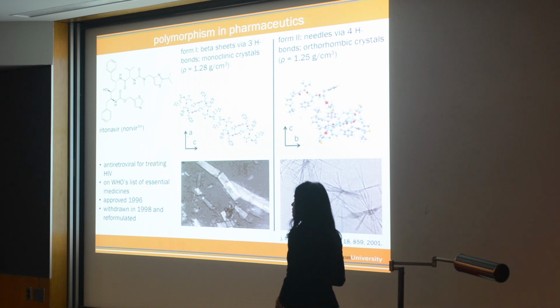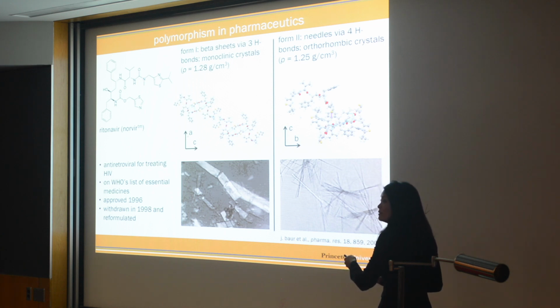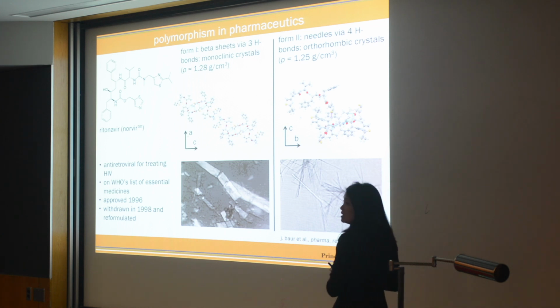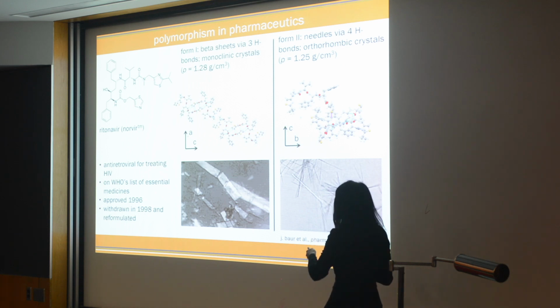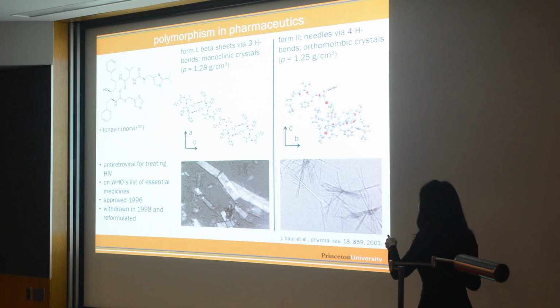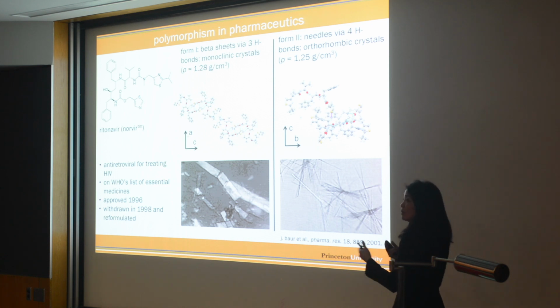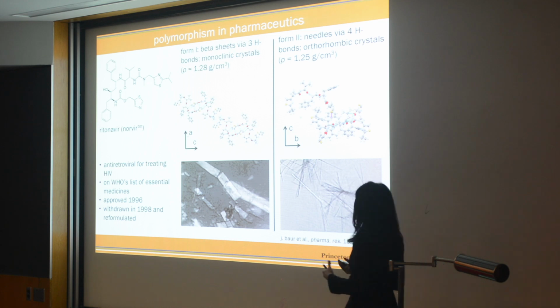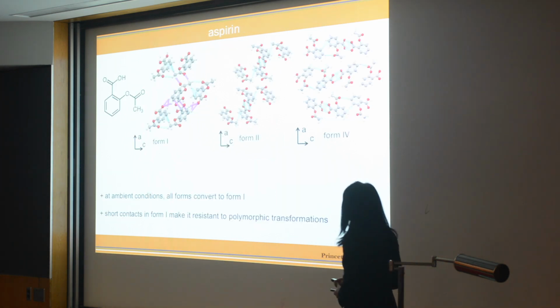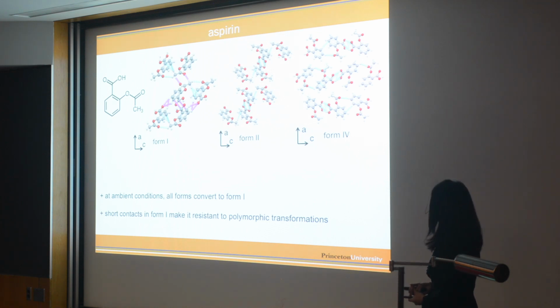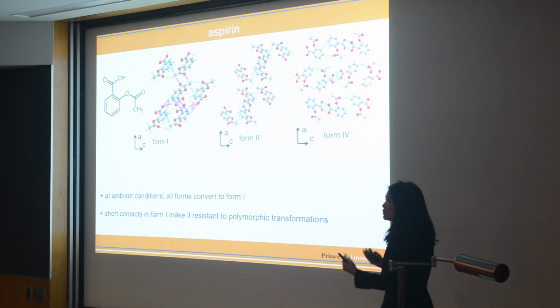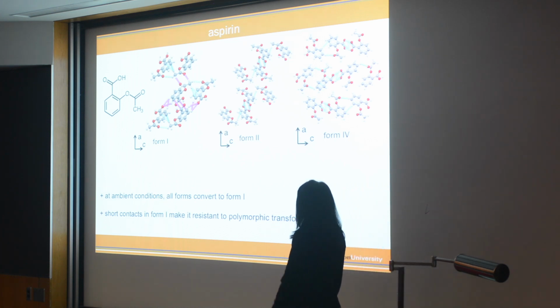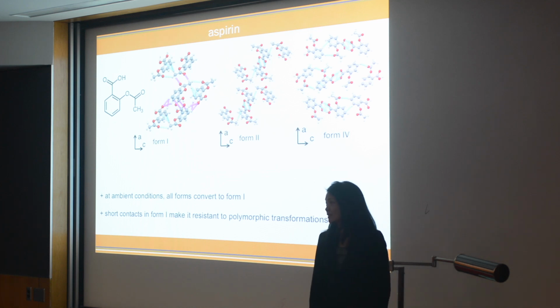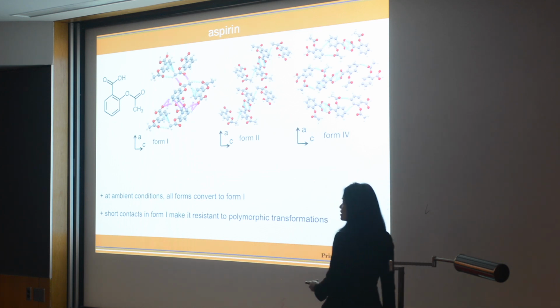Coming back to ritonavir, again, this is the antiretroviral drug for HIV. We don't see any short contacts in form 1, but we see short contacts in form 2. And so once there is a nuclei for form 2, it's going to convert into form 2 because we believe that these short contacts are there. Form 2 appears to be more kinetically stable, and that's the phase that sticks around. We can go to aspirin. Aspirin has 7 polymorphs. I'm showing you only 3 polymorphs here. And it turns out that no matter which polymorph you start out with, eventually at ambient conditions, you always end up in this form 1 polymorph. And under our framework, if you look for these short contacts, only form 1 has these short contacts.